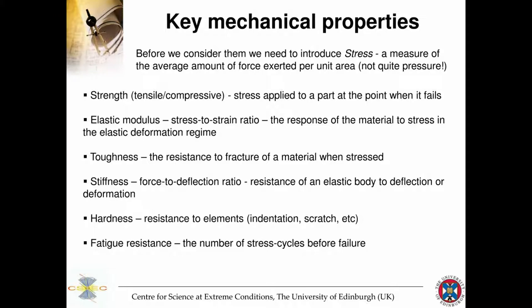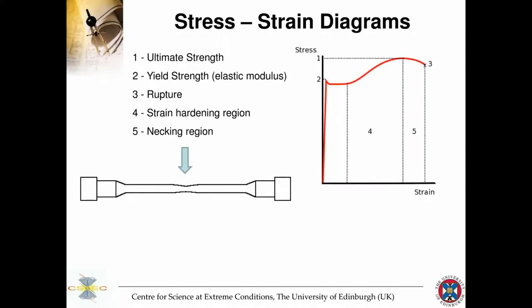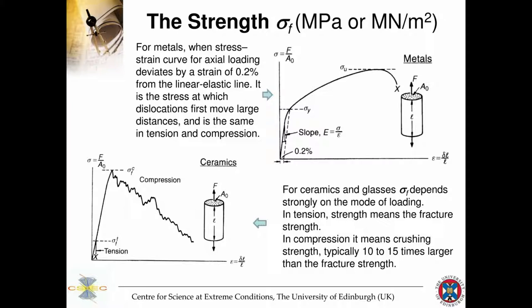The common stress-strain diagram plots stress versus strain — strain is the deformation and stress is the material's response. A hard material shows elastic deformation first, then plastic deformation, then rupture at point 3, with a necking region just before rupture — visible when doing a pulling experiment on a dumbbell-shaped sample. For ceramics, it looks slightly different: ceramics normally have no plastic deformation region and just fail brittlely.